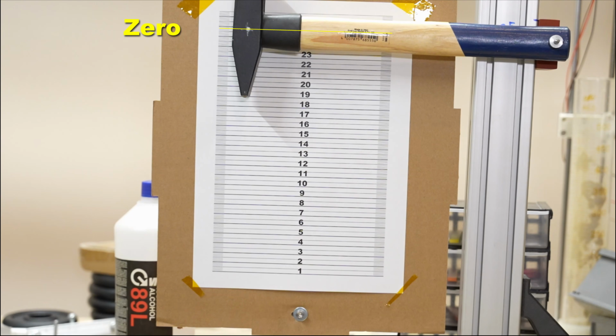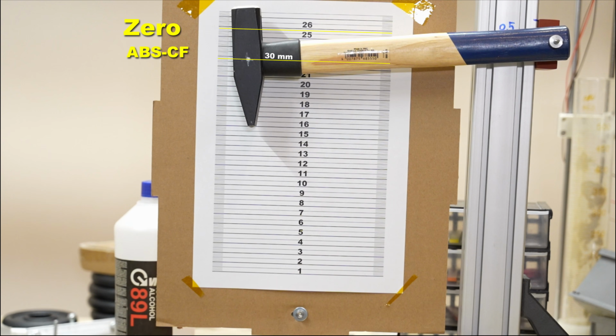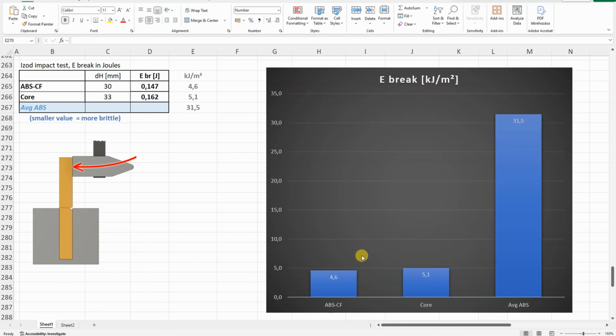This is the 0 position, and this is after breaking the ABS CF, and this is after the core version. And we can see that the core is tougher compared to the regular ABS CF, but both are quite brittle compared to the average ABS.